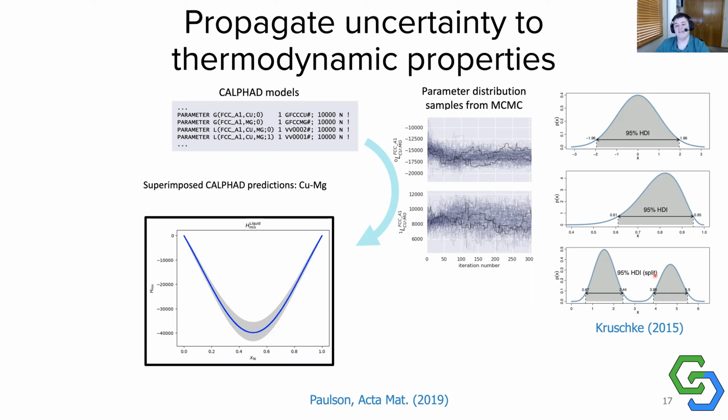And the meaning of these 95% HDIs and the width of your predictions is going to be tied to the width of your posterior distributions. And in turn, that comes from the weights and the uncertainties of the data and your priors, right? So there was a little bit of discussion in the chat during the break about how to handle this, and Richard mentioned that determining the weights is something that you can do precisely from error propagation analysis.